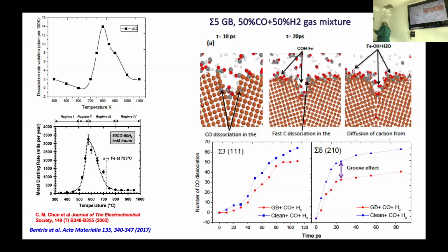So we were very lucky. We did some other work with Normand using kinetic ART, but this reactive force field, as I mentioned to you, was too unstable. With molecular dynamics simulations, we are using very small time steps of 0.5. But if we use it in the activation relaxation technique, we have a lot of inconsistencies and also fluctuations in the forces and energies. So this reactive force field did not work for us for kinetic ART.